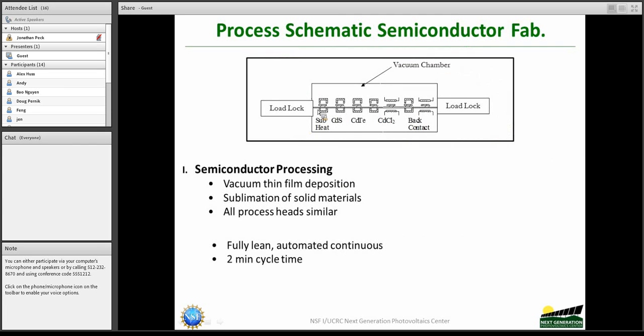where the glass comes in, it's heated. The first step involves heating the glass from room temperature to about 550 C, and this is done in about 2 minutes. Next, the glass moves to the cadmium sulfide deposition, where a thin layer of cadmium sulfide is sublimed onto the glass. Then it moves into this, where cadmium telluride is sublimed onto the glass.